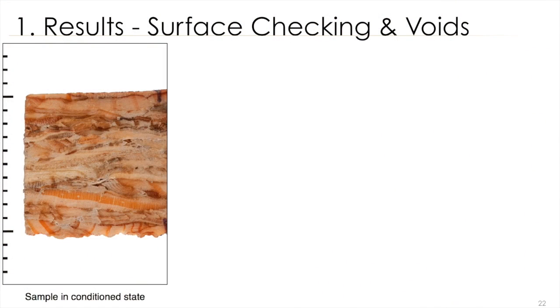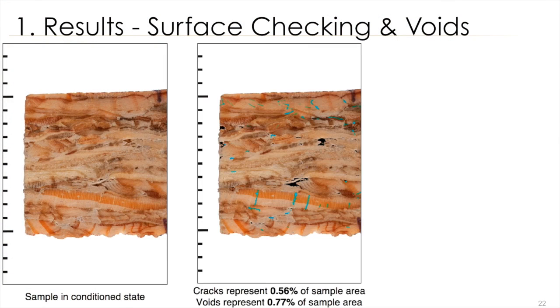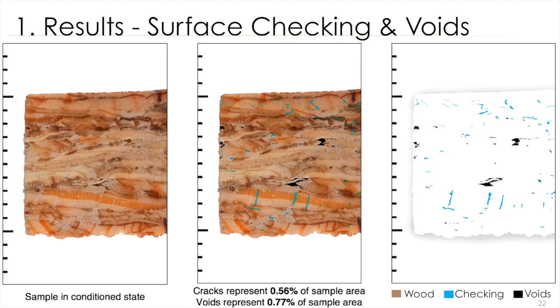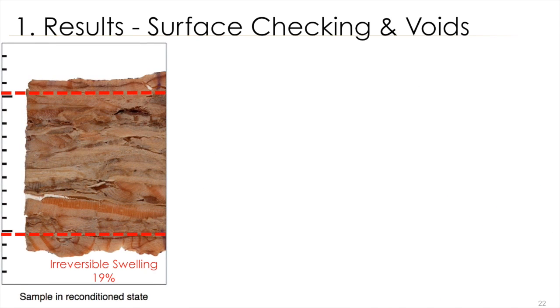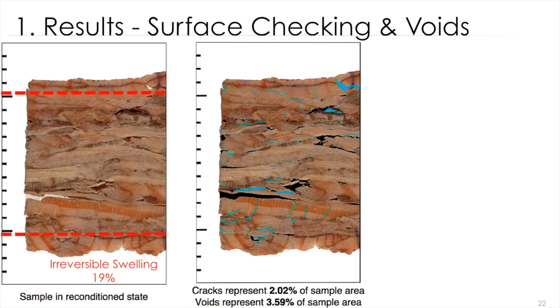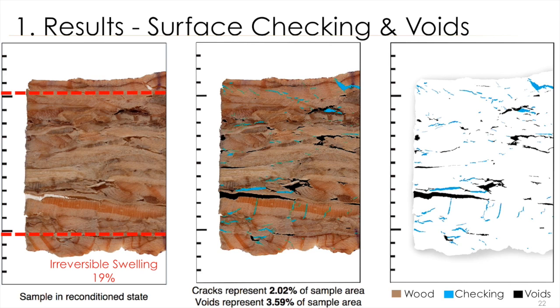Then I assigned surface checks and voids in the samples before and after the sample was reconditioned. So we can compare the area occupied by the checks and voids before and after swelling, and also the irreversible thickness swelling. In this case, 19% for this sample. As you can see, numerous microchecks developed in OSB exposed to wetting and drying, as I hypothesized. So the area occupied by checks directly impacts change in dimensions.